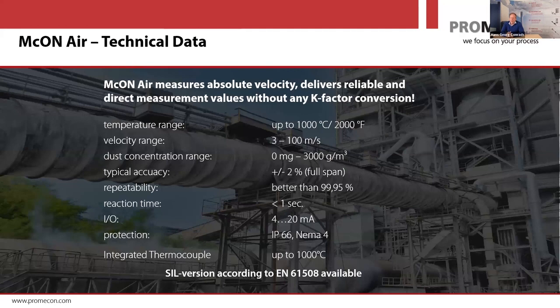So basically what we have here is a flow measurement that can measure up to temperatures of 1000 degrees Celsius, in a velocity range of 3 to 100 meters per second, completely linear. We have a huge turndown ratio because we do not have any squared relationships that you might have with delta P systems. With a very high accuracy over the full span, and needless to say, an outstanding repeatability.